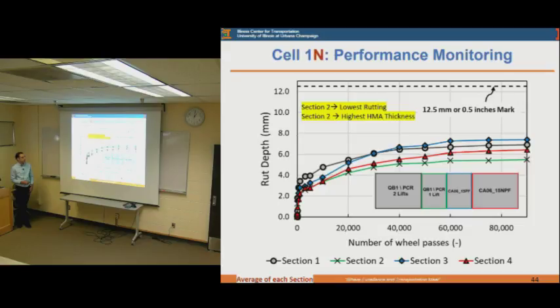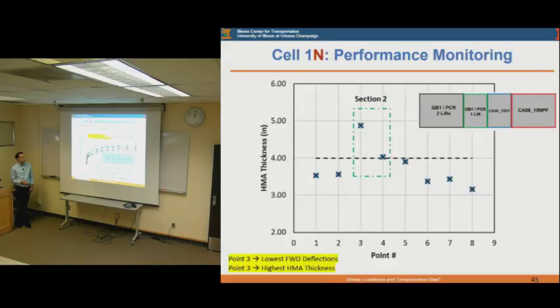What we saw in these test sections is that the lowest rutting was in section 2, this time not in section 4, which has the core byproduct mixed with the primary crusher runs constructed in one lift. Part of the reason for this was the higher HMA thickness on top of this section than section 4. And all 4 sections performed pretty similar, I would say. The maximum rutting was around 7 millimeters, the minimum was around 5, and they had similar rutting.